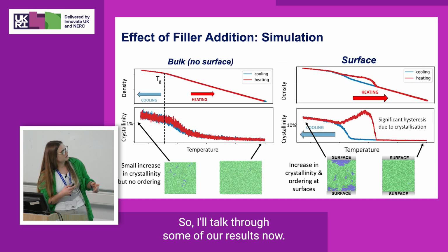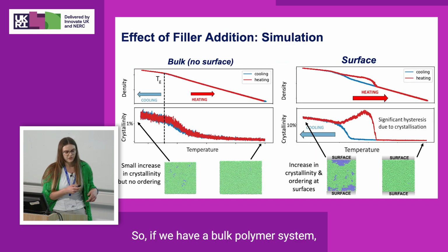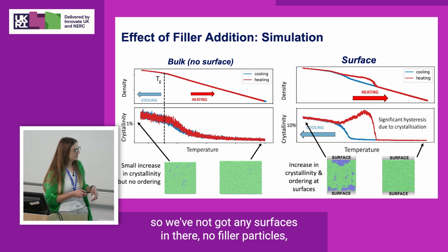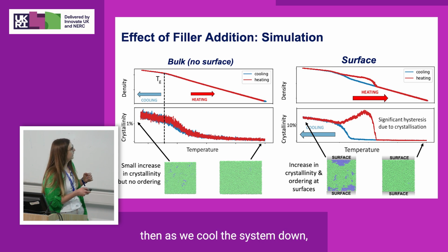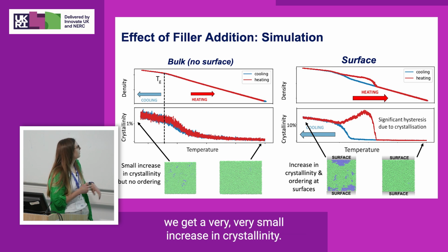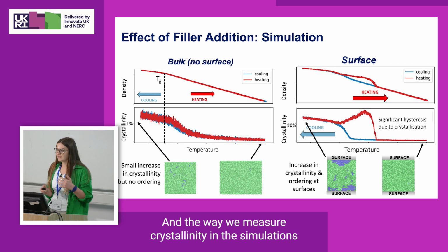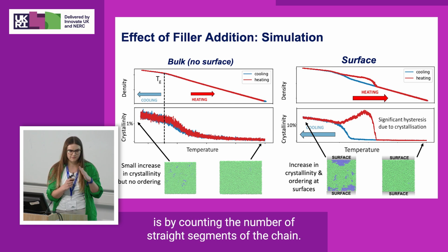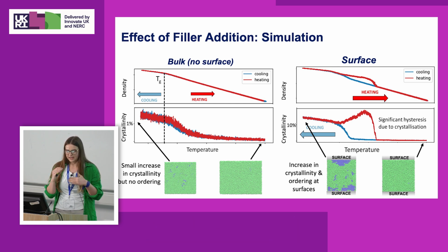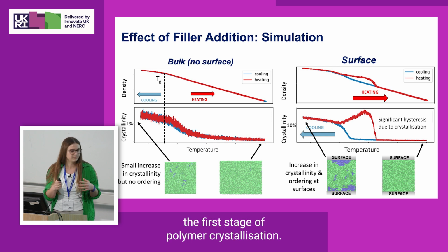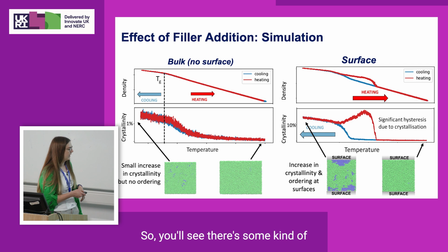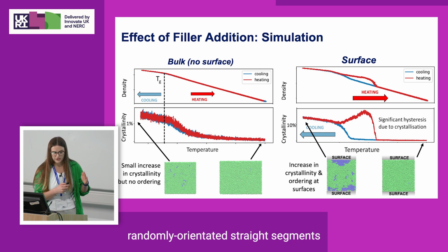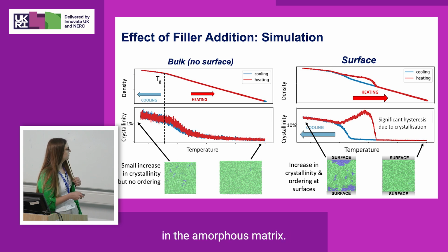So I'll talk through some of our results now. If we have a bulk polymer system, so we've not got any surfaces in there, no filler particles, then as we cool the system down, we get a very, very small increase in crystallinity. And the way we measure crystallinity in the simulations is by counting the number of straight segments of the chain. So that's thought to be the first stage of polymer crystallization. So you'll see there's some randomly orientated straight segments in the amorphous matrix.